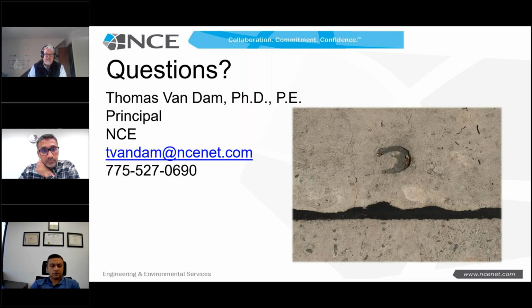And I will also add, though, if you drop that water cement ratio below about 0.5, which you should be doing for structural steel, the level of carbonation is pretty small. And there's other people investigating how we can carbonate the concrete when we recycle it. So this is all a very active area of interest in research. So you can spin yourself around. But yes, that was a very observant, good question.